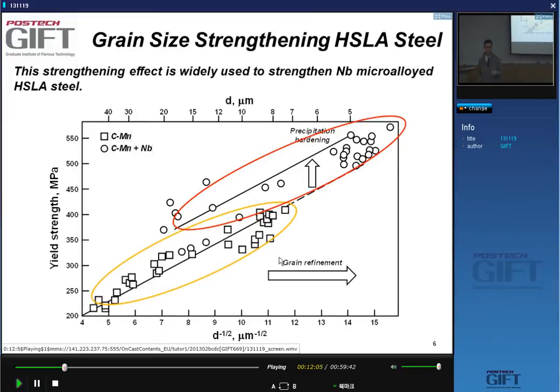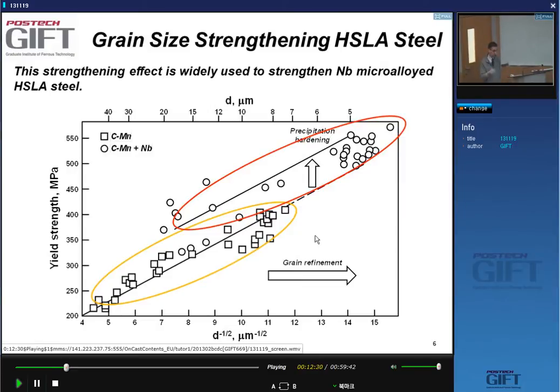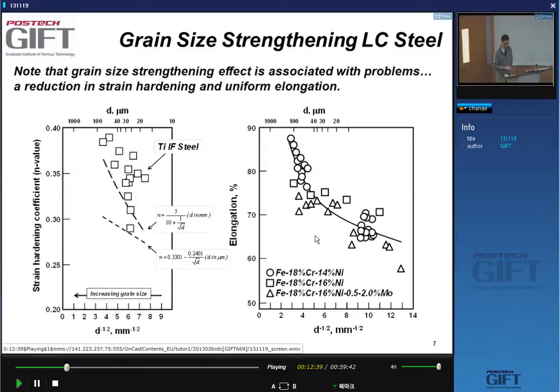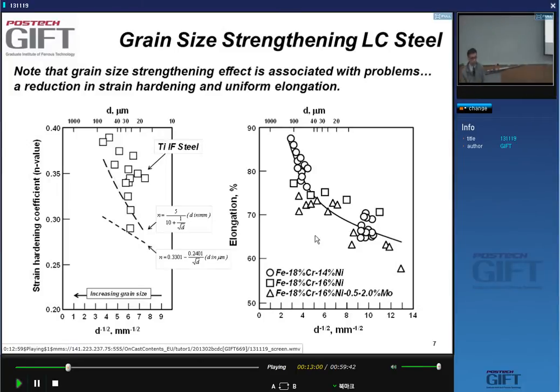Strengthening by reducing grain size is very common, and the clearest steel grades where this is done are niobium-alloyed grades — not only sheet material but plate material as well. Many grades have niobium added to obtain grain refining through thermomechanical processing. We have methods to control grain size, making it smaller down to 5 microns. So grain size reduction gives you strength, but it doesn't give you formability.